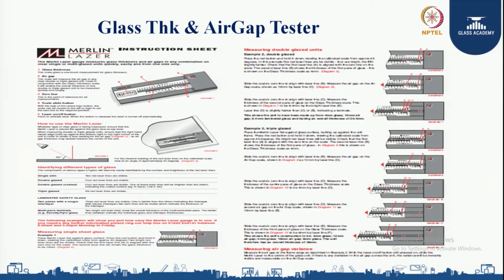For a single glazing unit, you get 2 surfaces, thereby 2 lines. For a double glazing unit, you get 4 surfaces, thereby 4 lines. For a laminated DGU, you get 6 surfaces, thereby 6 lines. For a double lami DGU, you get 8 surfaces with 8 lines. This is how you trace out the glass thickness as well as the air gap inside the DGU. This concludes all the tests that we do for a DGU glass make.